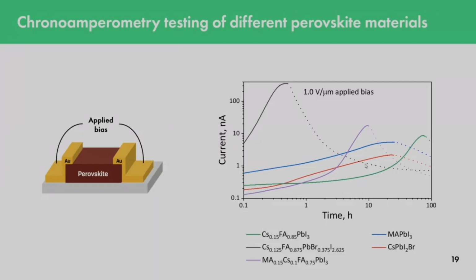and applied electric bias. And first of all, we decided to observe the change of the current in the channel while applying this electric bias to the gold electrodes. And we can see that all materials demonstrate similar behavior. So at the first times of bias application, the current is increasing, but after some point, different for every material, the current starts to decrease.